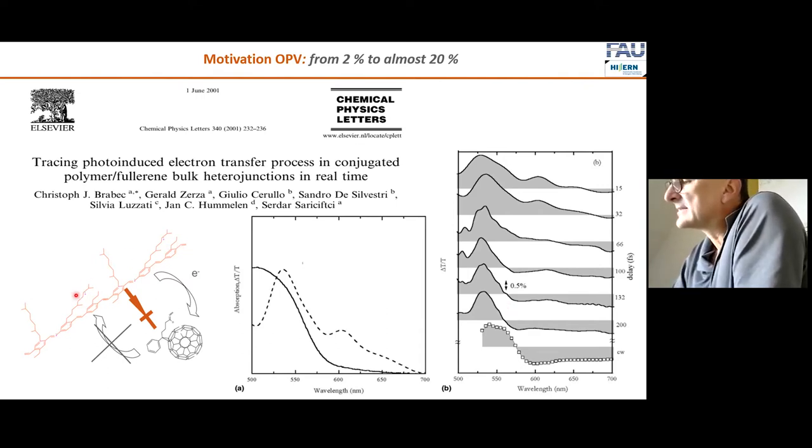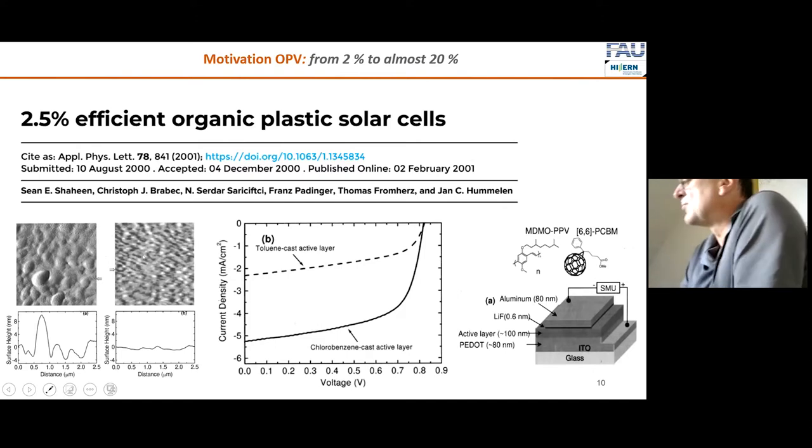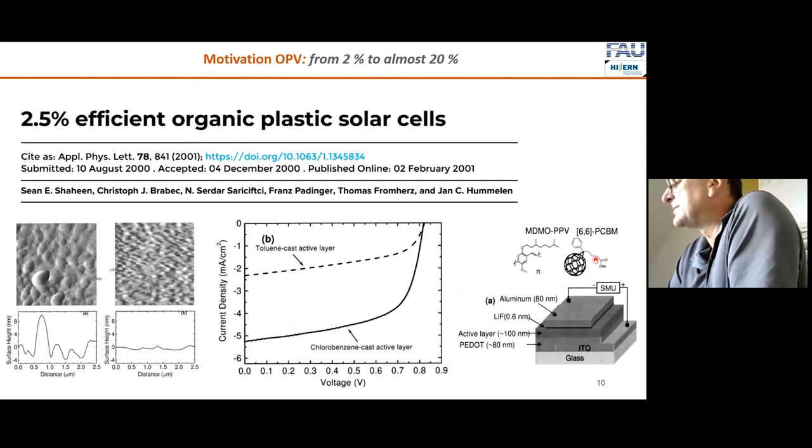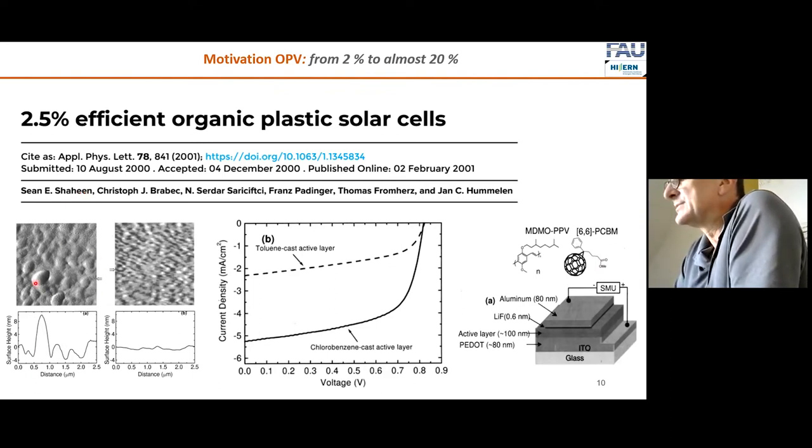So the free charge generation rate in a pristine material is below 0.1%. Now when you mix two semiconductors with preferential potential differences, you can get a charge transfer which has a quantum efficiency of up to 100%. And we could verify why this is the case, and the case is you see in the transient pump-probe spectra, this is the case because it's really fast. You can see here, this is the trace where the CT is kicking in, and it's happening at a time delay of some tens of femtoseconds. So it's very fast, and this is the reason why it is so efficient.